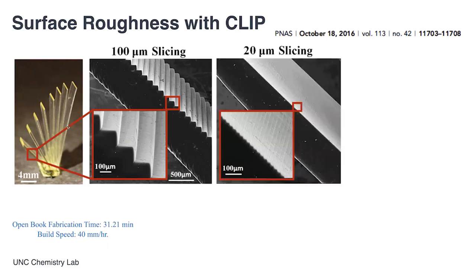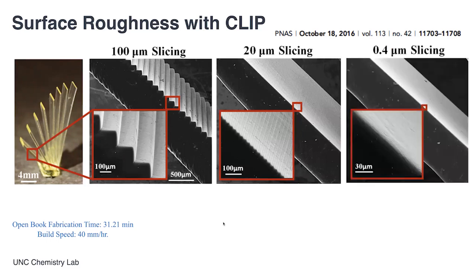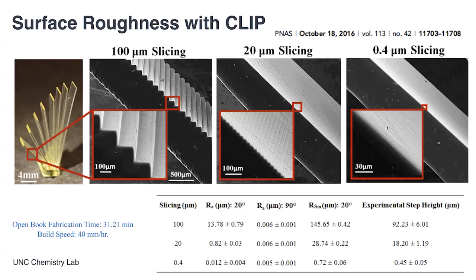Well, we could slice that image 5 times more frequently so that the image is changing more quickly. Or we could slice it even thinner, and now the images are changing dramatically. But we're making these all at the same rate, at 40 millimeters an hour. We're just changing the images more quickly. If this were a traditional 3D printer and you changed your resolution from 100 micron slices to 1 micron slices, you would slow down the printing by a factor of 100. Here, we're keeping it constant. We're actually going continuously. And with that, you can get to amazingly smooth surfaces.